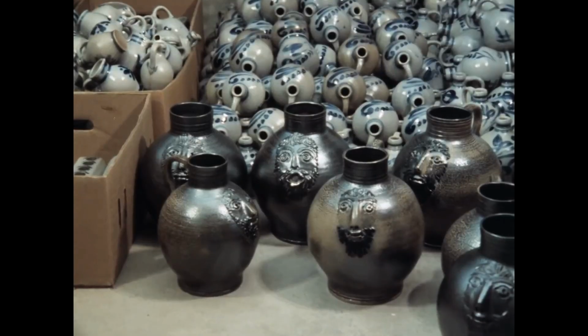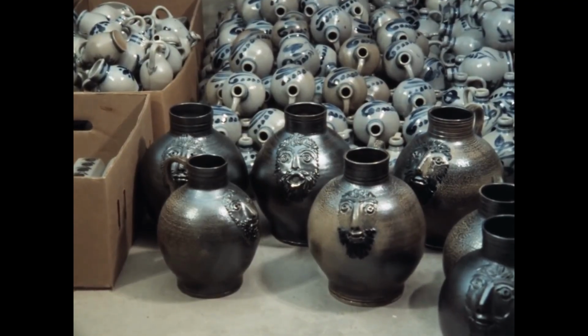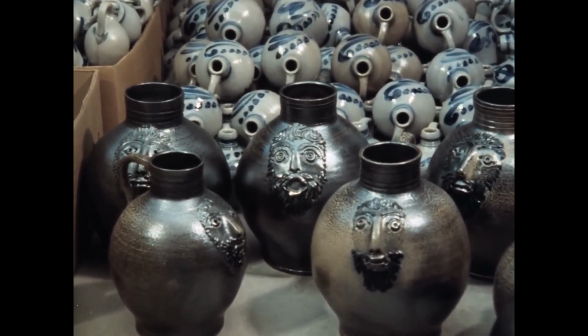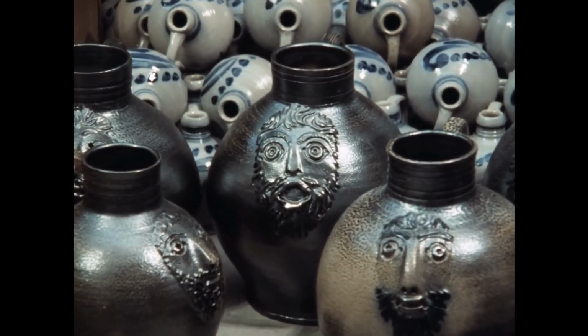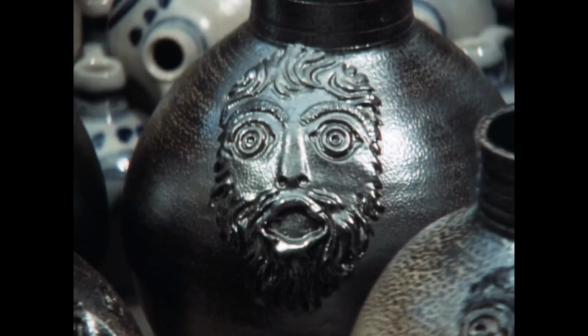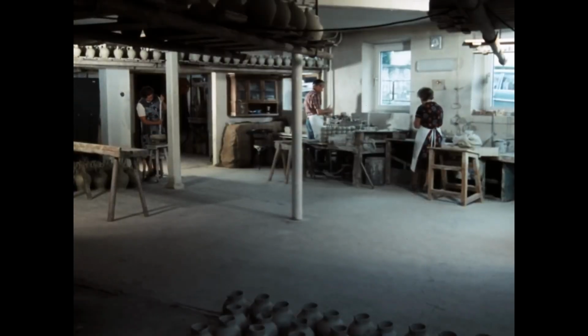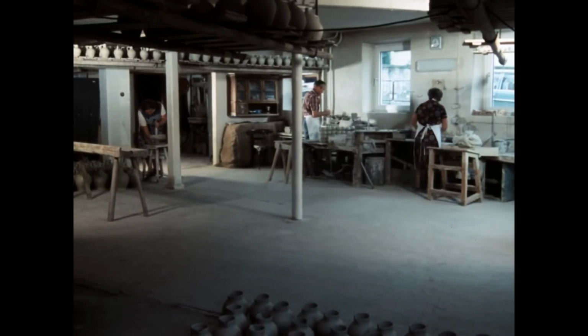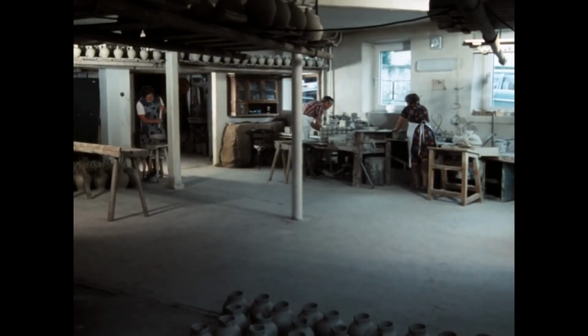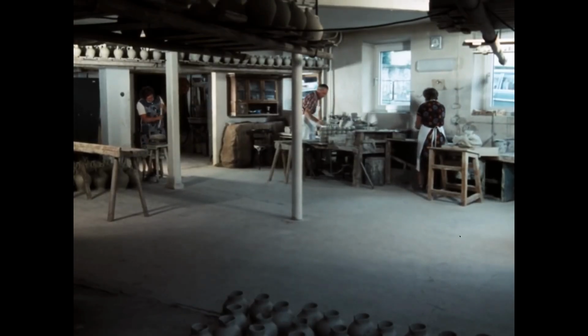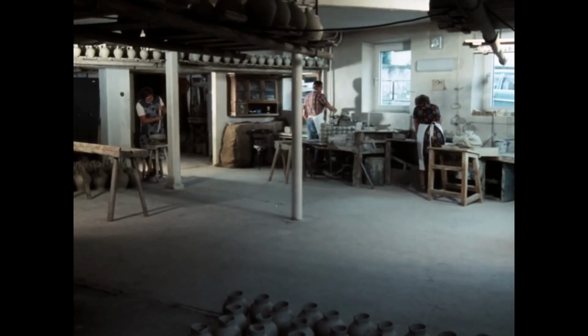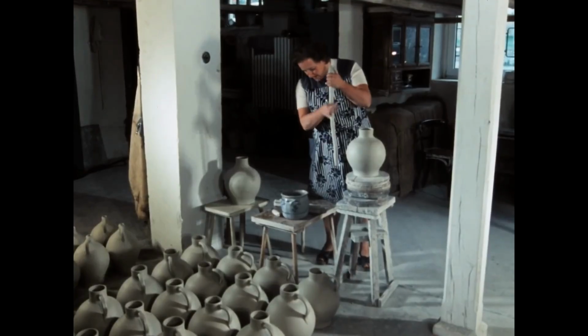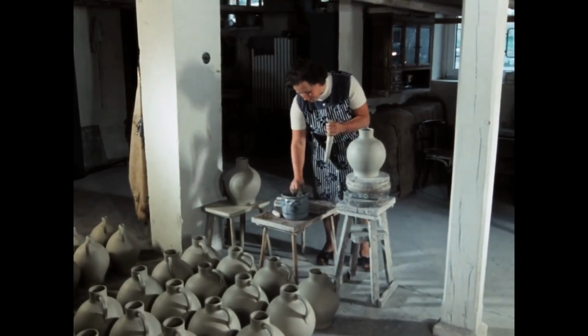The brown skin of the fired jug is not painted on. It is the result of chemistry. At peak temperature, 1,200 degrees Celsius, sodium chloride is thrown directly into the open kiln chamber. The sodium bonds with the molten quartz on the vessel surface. It forms a glass layer, salt glaze, permanent, integrated into the clay itself. Not applied after firing, grown during it. Without the salt, the stoneware would emerge dull and porous. With it, sealed, hard, and reflective.